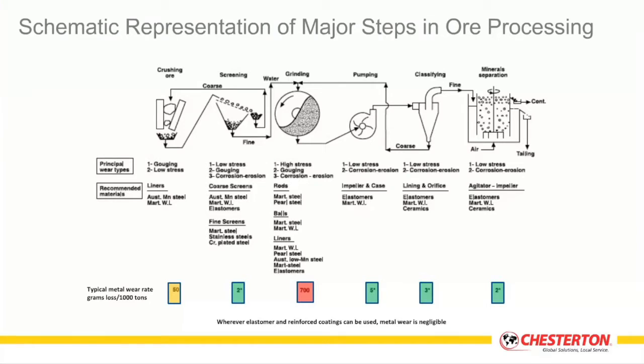And then you'll see finer and finer wear rates, where the wear rates are typically less than 5 grams of loss per 1,000 tons of ore processed. So the primary areas we'll focus, where you'll see heavy wear, will be grinding and crushing, and then lower wear rates in the screening and the pumping and the classifying and separation phases.